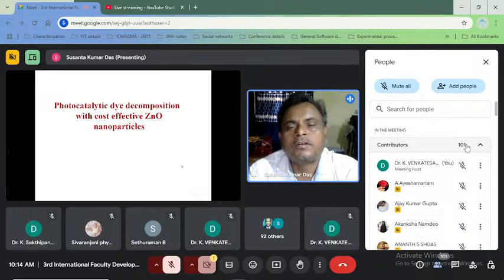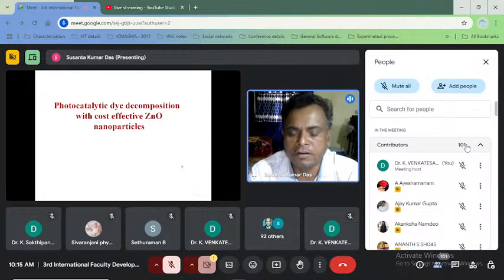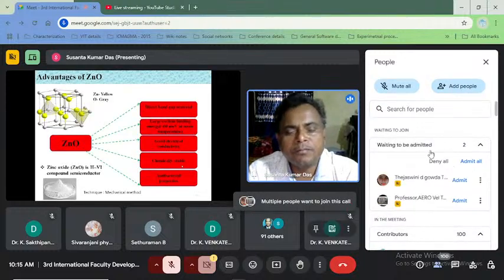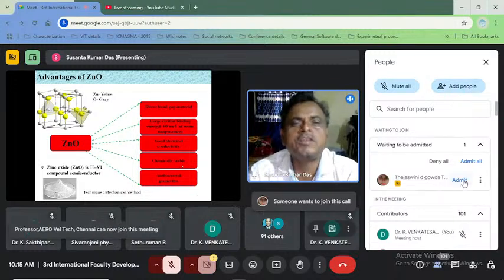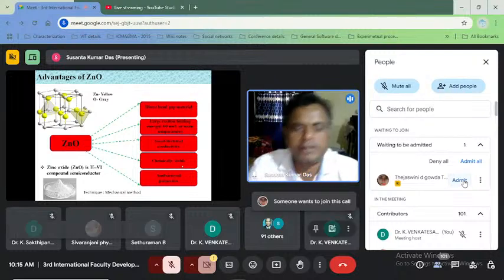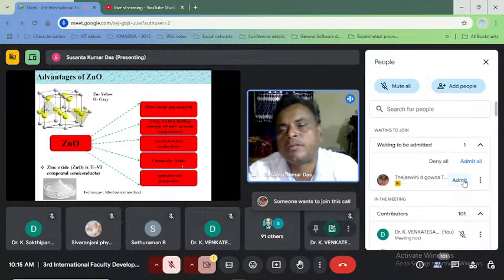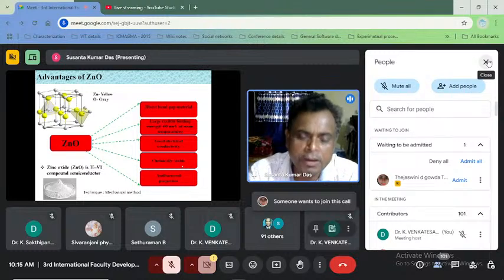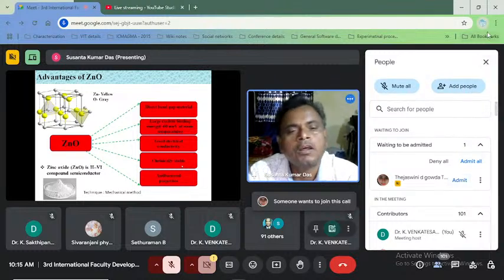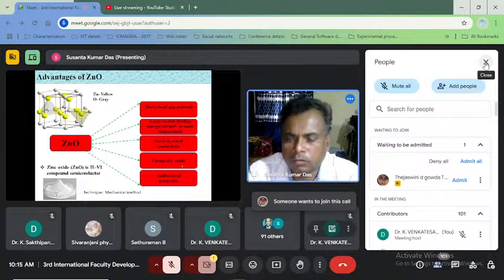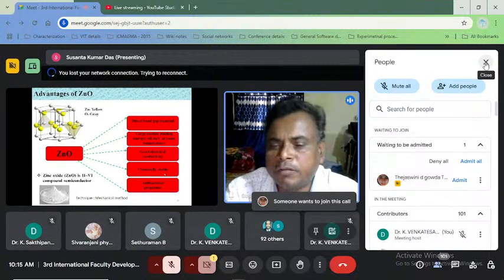Now coming to the work, I would like to start with photocatalytic dye decomposition using cost-effective zinc oxide nanoparticles. Probably many of you are new to this field, so let me tell you, zinc oxide is a compound semiconductor. It's a wide band gap semiconductor material. It's a direct band gap also. When it is a direct band gap, its photon absorption capability is more. It has a large exciton binding energy and good electrical conductivity, good chemical stability, and